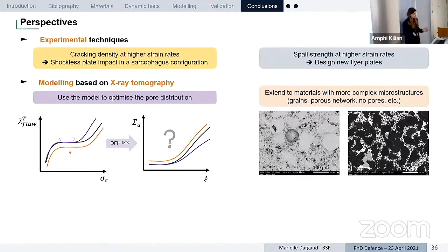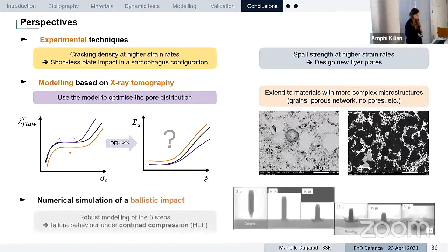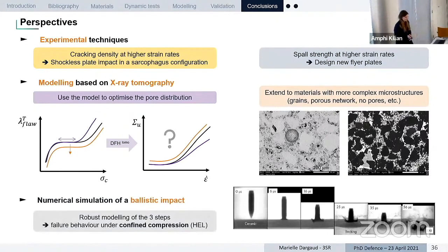We can also extend this approach to other types of material. Here we are on, let's say, ideal microstructure with pores as our main defect, but we could extend by some adaptation this approach to materials presenting a mesostructure where the size of the grains is going to have an influence, or the different phases are also going to have an impact on the failure behavior. In the end, the main goal is to reach a numerical simulation which is realistic compared to ballistic impact. And we saw that the ballistic impact is divided into three main steps. So here we need to extend this work to have a robust modeling of the compressive behavior under confined compression. Well, for the tensile behavior, this is what we did today. And for the behavior of the fragmented ceramic.